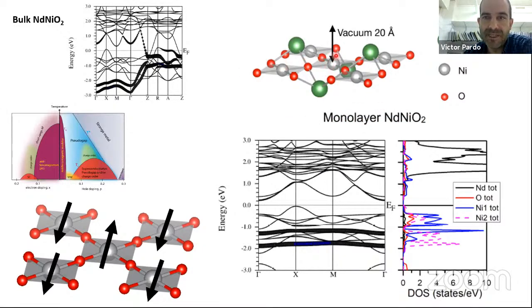In that way, you basically kill the off-plane hopping. The off-plane hopping is what is producing these hugely dispersive d z-squared bands, which are the ones highlighted here in this band structure. And indeed, if you have a single layer of neodymium nickel O2, the d z-squared bands become really flat. They cannot hop along the c-axis, and the system is an antiferromagnetic insulator with this checkerboard spin pattern in the plane, just like in the cuprates. So this point in the phase diagram that is characteristic of the cuprates also exists in these nickelates. What you need to introduce is a dimensionality ingredient.